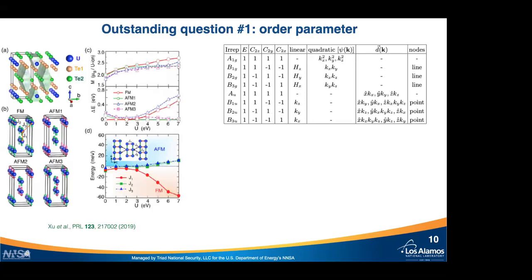And I want to point out that even before our paper came out, initial DFT plus U calculations, and this is density functional theory calculations considering an on-site Coulomb interaction U, tried to find various combinations or configurations of the spins. Again, remembering that we have this chain along the A-axis and the dimers along the C-axis. And here in figure C, you can see that it's actually not energetically favorable for the system at high Coulomb U to be in the ferromagnetic state. And this is very in line with what we see experimentally. So now, again, remember with pressure here, we are actually increasing the Coulomb U, not decreasing it. So the system is becoming more localized, and we don't see a ferromagnetic state. We see an antiferromagnetic state.